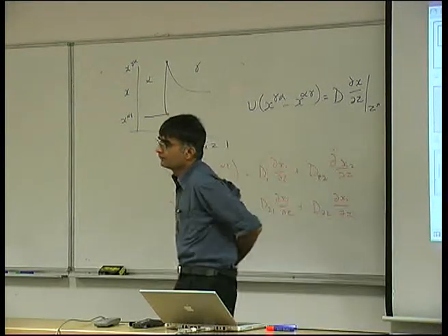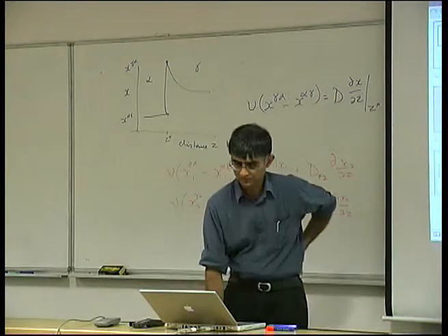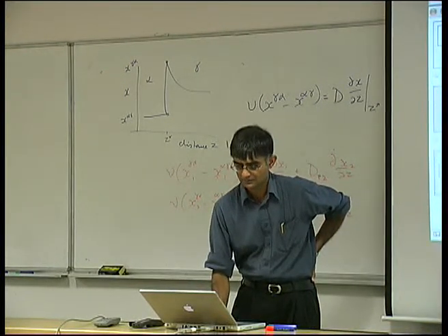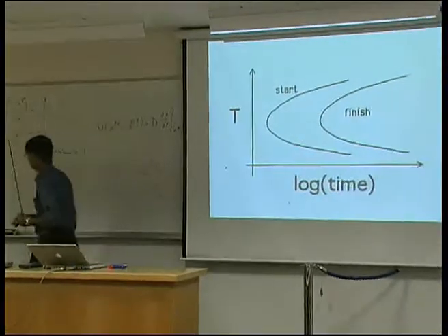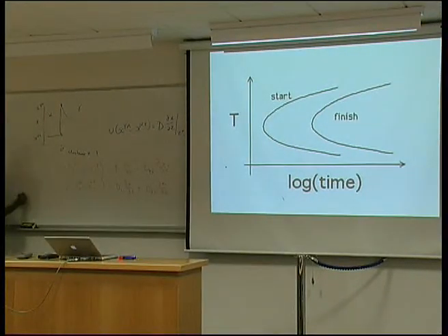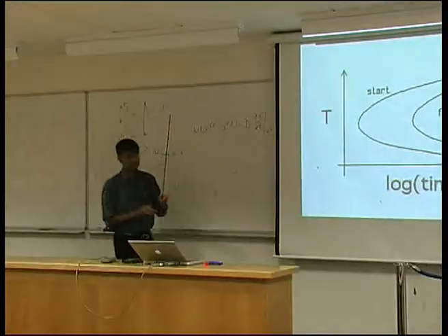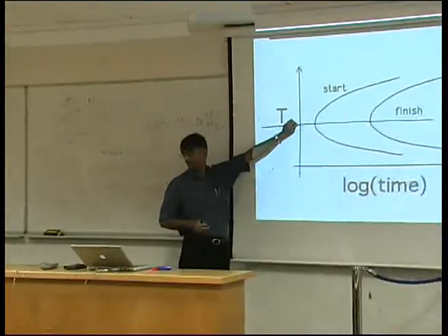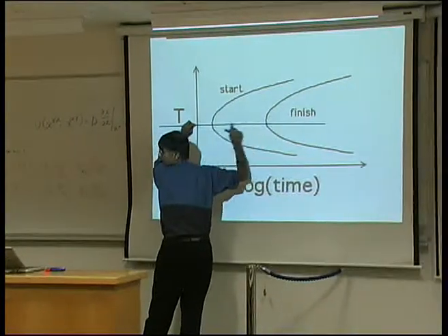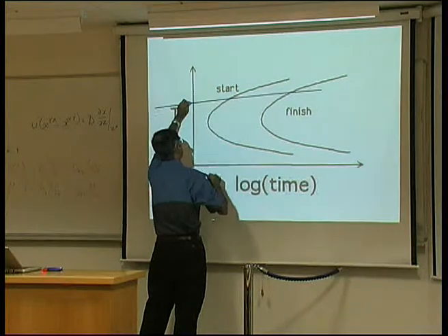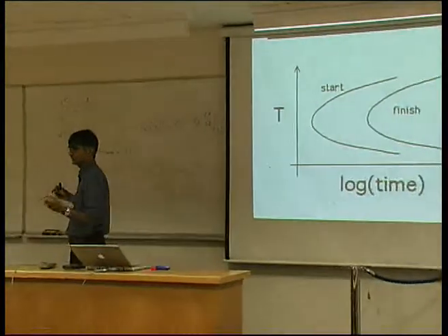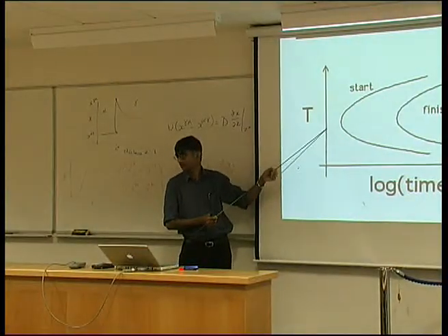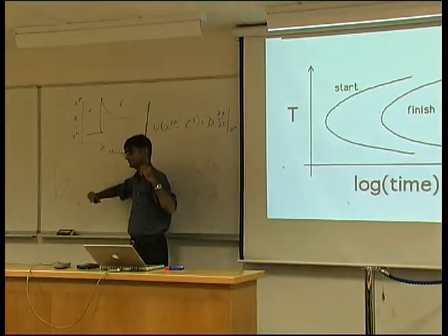I just missed, what does the isothermal transformation diagram represent? So this diagram is constructed by doing either a calculation or a measurement of the evolution of volume fraction as a function of time. If I take that curve and plot it at a certain temperature, I get these two points, or any point in between. I do that at another temperature, then the kinetics are different, so I have these points, and I generate the isothermal transformation diagram. So it's taken by supercooling the parent phase, holding it at that temperature, and getting this curve.